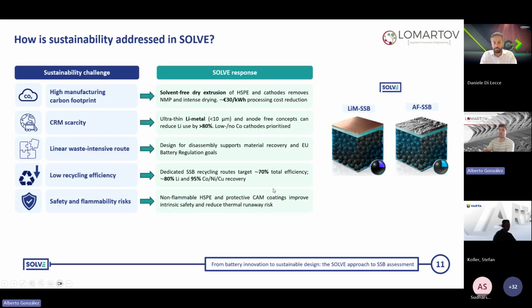So the question is, how does SOLVE address these sustainability challenges that I presented? Well, sustainability is integrated into every step of the project, from the materials we select in the lab to the manufacturing routes we choose, and right through how we plan for the battery's afterlife. We are moving away from traditional wet methods and exploring solvent-free dry extrusion for both the hybrid solid polymer electrolyte and the cathode. And this is a massive step forward because it allows us to avoid toxic solvents like NMP, and skip some energy-intensive drying steps. This approach could slash the processing costs by around 30 euros per kilowatt hour of delivered energy.